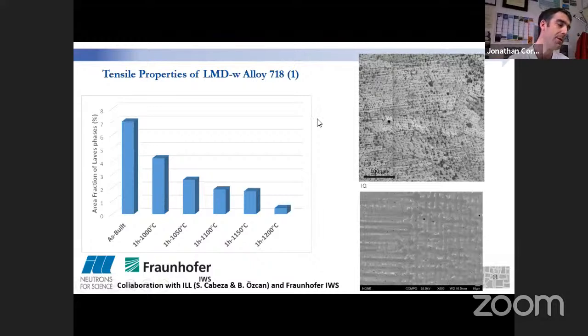So first of all, what we did here, we tried to develop heat treatments to be able to get rid of this kind of phases. Here you have a typical evolution of the Laves phase content, starting from 7–8% in the as-built state. We can see a progressive decrease of the Laves content with increasing solution treatment temperature. We cannot go in excess of 1200 C, the problem being that we would reach incipient melting. So in the following slides, I will show you that we are using solution treated specimens to understand the properties, with the solution treatment being 1 hour at 1200 C.